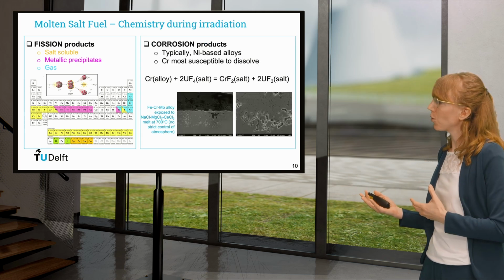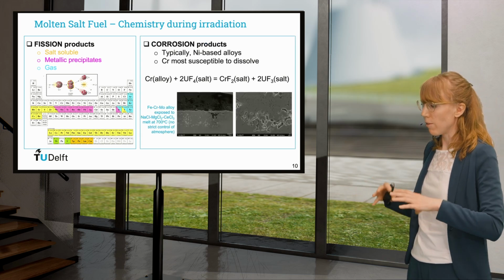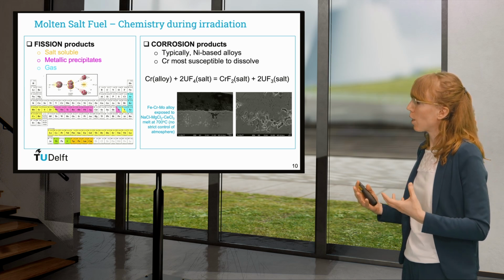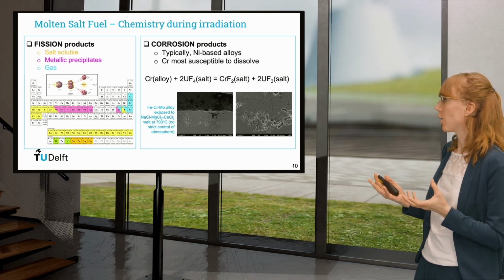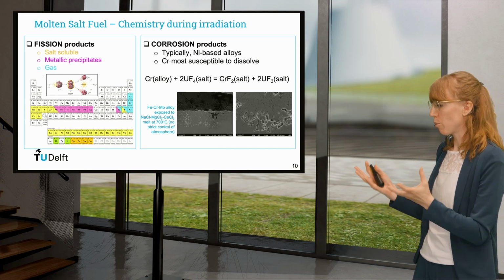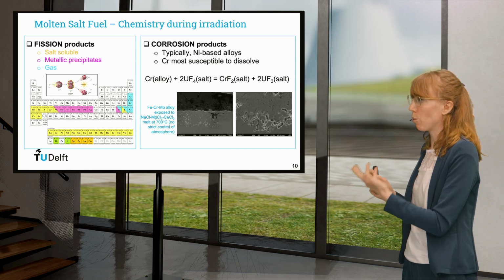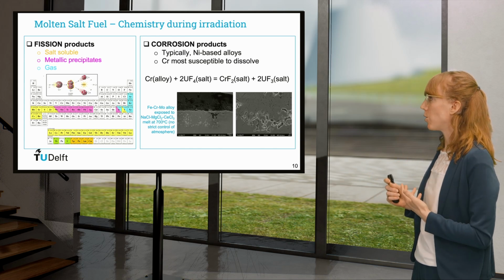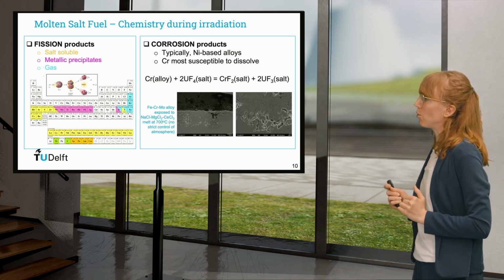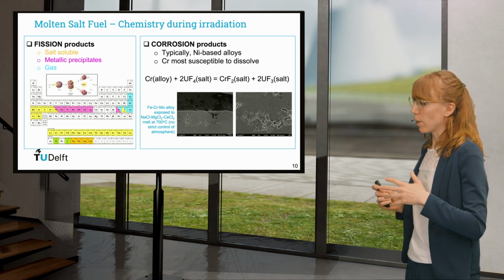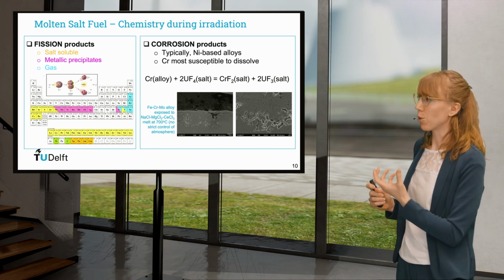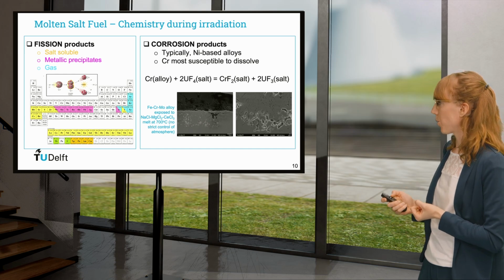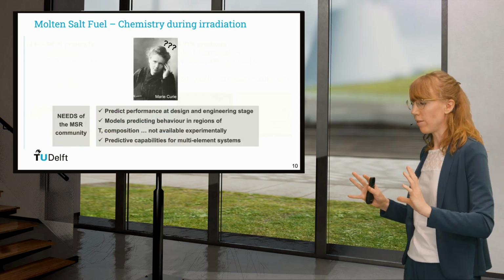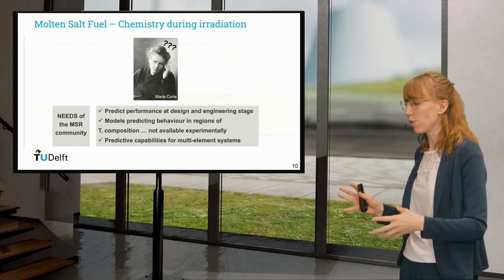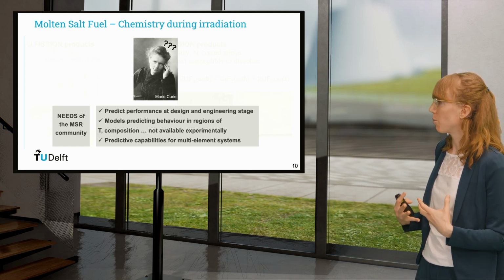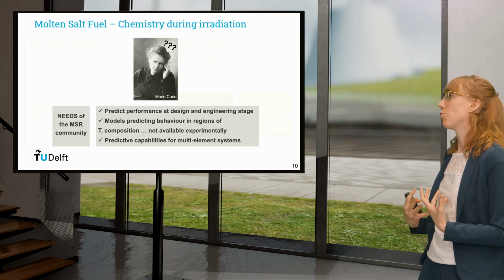And next to these fission products, you also have corrosion products. These accumulate after some time in the salt because this salt is highly corrosive. Typically, the structural materials you can use around the salt are nickel-based alloys, but in these, some elements like chromium are going to dissolve into the salt. So that will mean that these corrosion products will also affect the properties of the molten salt. So you can already see that we have the molten salt fuel with many elements. We add fission products, we add corrosion products. That makes a very complex chemistry.